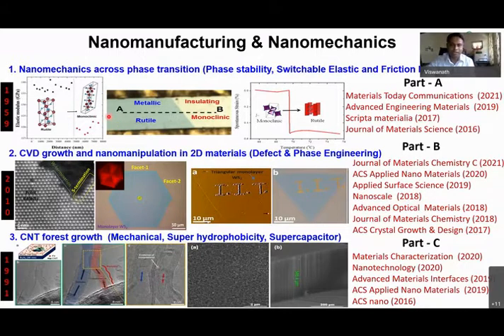The phase transformation can be triggered by multiple stimuli. We often use heating or temperature in order to induce the phase transformation. So we can use nano indentation to measure the properties as a function of temperature with a heating setup and so on. It is also possible to stabilize both the metallic and insulating phases, otherwise rutile and monoclinic in terms of structure, at the same temperature.